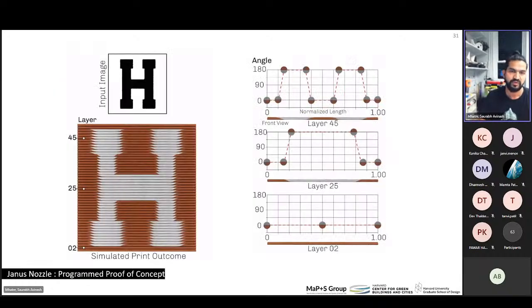Knowing this, we decided to create a proof of concept of our research. To be able to take in input a black and white image, and the script would divide the image into horizontal tool paths. The rotation of the nozzle 180 degrees at the fringe of the black and white pixels was the main agenda. So as you can see in layer number 45, at the intersection of where the white pixels change to the black pixels, there would be a change in the fourth axis of 180 degrees, and hence it would cause a change in the body of clay that's visible in the front elevation.